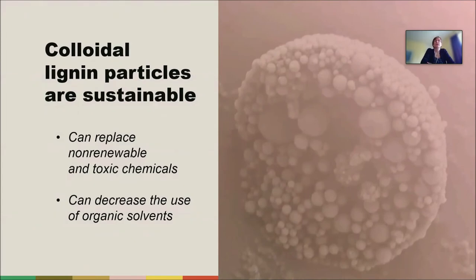So to conclude about colloidal lignin particles, they are sustainable and they can replace non-renewable and toxic chemicals in many applications. I only showed you a few examples, but we can make very good adhesives, for example, so that we can get rid of volatile organic compounds, but only have this natural lignin. And this can also decrease the use of organic solvents. So I see that there's a lot of potential with the lignin. And as you saw in the example of the coating, of course, lignin can also be a colorant. So here we can combine the color and the functionality.